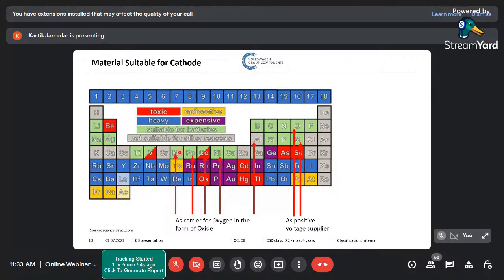And as we know that the cobalt prices are increasing to the heavens, so everyone wants to reduce the cobalt and increase the nickel. Nickel is giving me the main energy. But as you increase the nickel content, you also decrease the safety of the cell. So it has to be compensated by either a little bit of cobalt or a little bit of manganese. And that's why at present the standard technology is called 811: 80% nickel, 10% cobalt, 10% manganese.